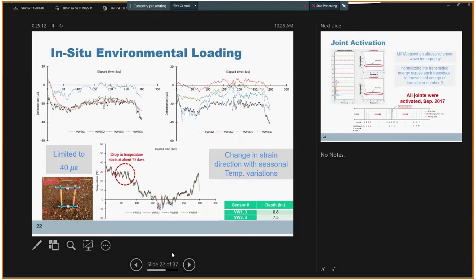We also monitored the data collected from vibrating wire strain gauge sensors embedded at different depths and different spots of these pavements. It was interesting to see that the direction of the strains and deformation is following the pattern of variation in environmental conditions, environmental temperature. After about 75 days of casting, the cold season started, and there was a drop in environmental temperature, and this coincides with the time that the deformation patterns change. Again, we had comparable data, similar for sensors located at similar spots of these two experimental pavements.